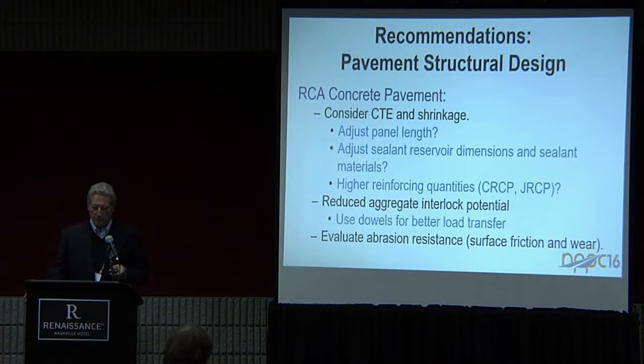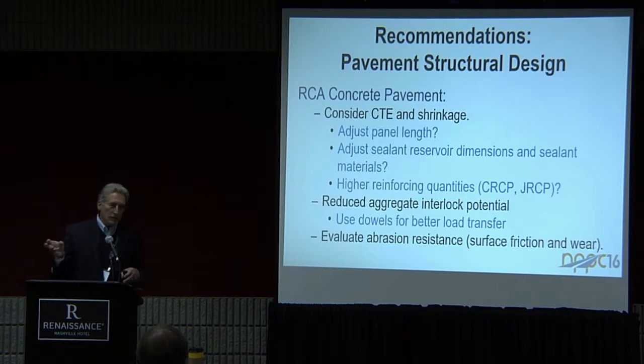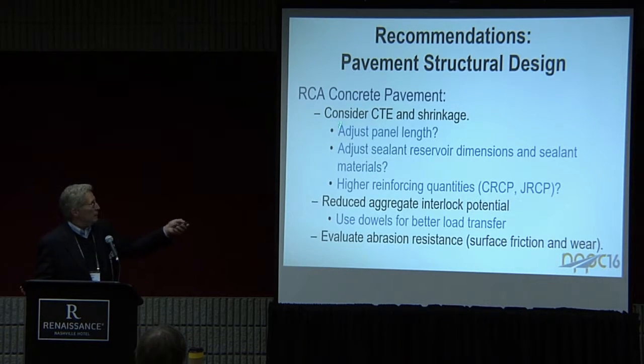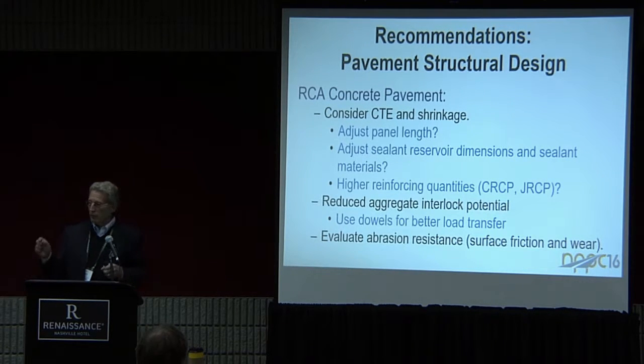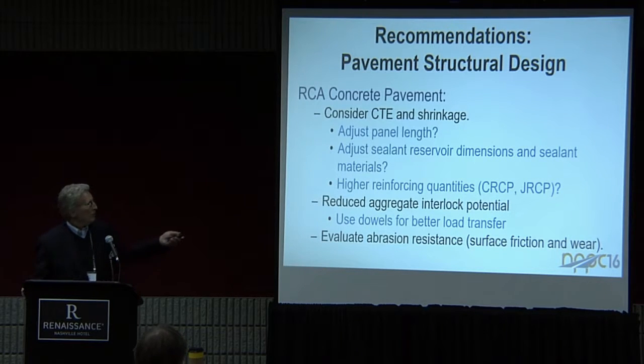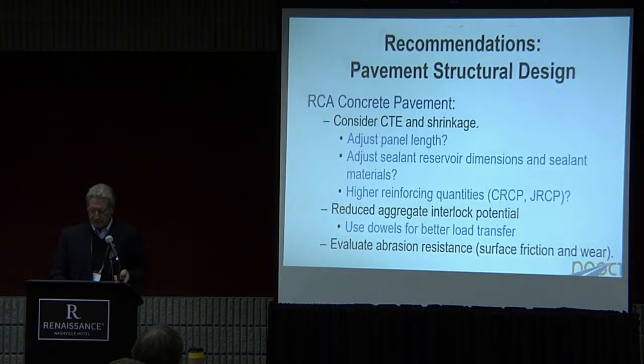From a structural standpoint, we also need to consider the impact of the behavior of the concrete on the design of the pavement. Typically it has a little higher coefficient of thermal expansion and contraction, and a little higher shrinkage coefficient, which might mean we need to adjust the panel lengths, bring those down a little bit. Maybe we need to adjust our sealant reservoir dimensions if we're sealing our joints. If you've got a little more movement taking place, you might need a little wider reservoir on your sealant so that it accommodates that movement. You might want slightly higher reinforcing quantities in your continuously reinforced and jointed reinforced pavement. Okay, so those kinds of things.